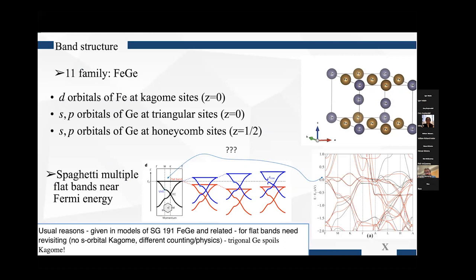Now, if you have a kagome lattice, and the kagome has obviously a flat band, if you put something in the trigonal lattice and couple the kagome lattice to a trigonal lattice, you're not going to get flat bands anymore. That's the line graph principle. You're smashing up the line graph principle by putting a trigonal lattice on the kagome, so you're not going to get flat bands. Now we can argue that there's weak coupling between these, but we'll see in the effective models that there's actually not such weak coupling between iron and germanium.